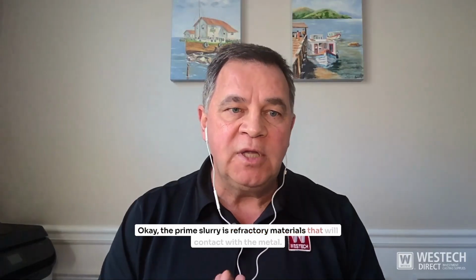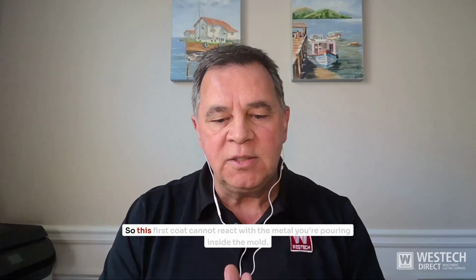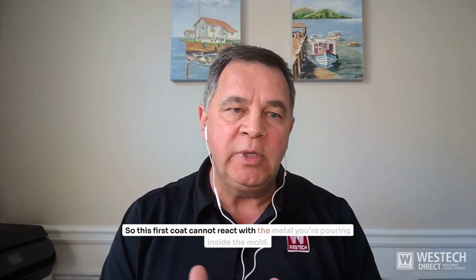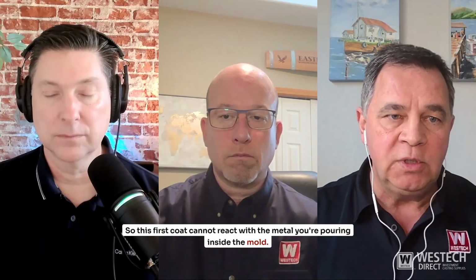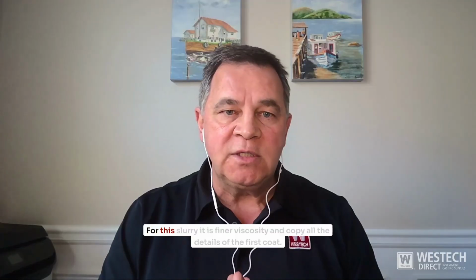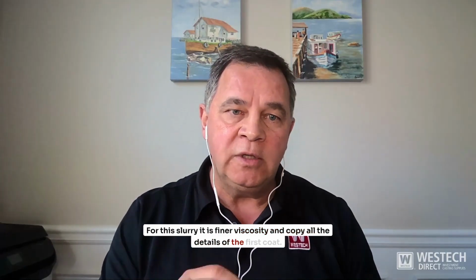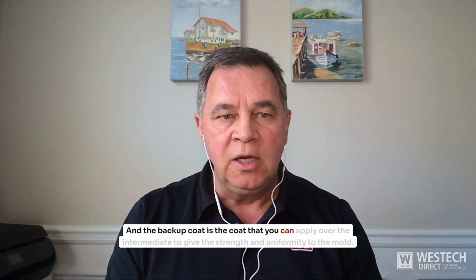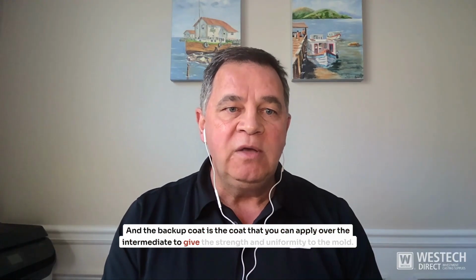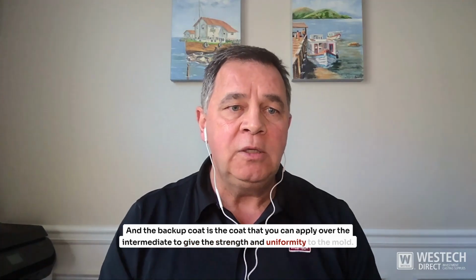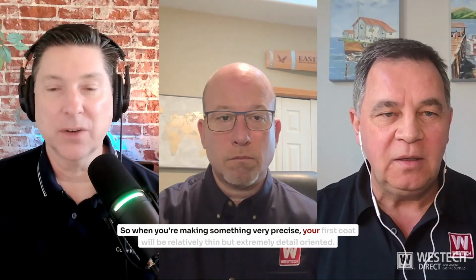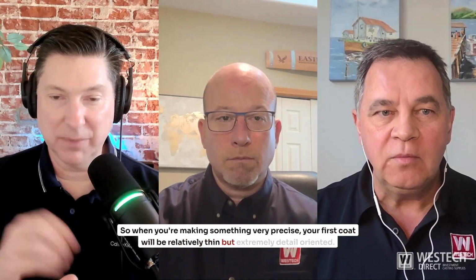Okay. The prime slurry is the refractory material that will contact the metal. So this first coat cannot react with the metal you're pouring inside the mold. We call the intermediate slurry the slurry that has a thinner viscosity and copies all the details of the first coat. And the backup coats are the coats that you apply over the intermediate to give strength and uniformity to the mold. So when you're making something very precise, your first coat will be relatively thin but extremely detail oriented. Is that right? Yes.